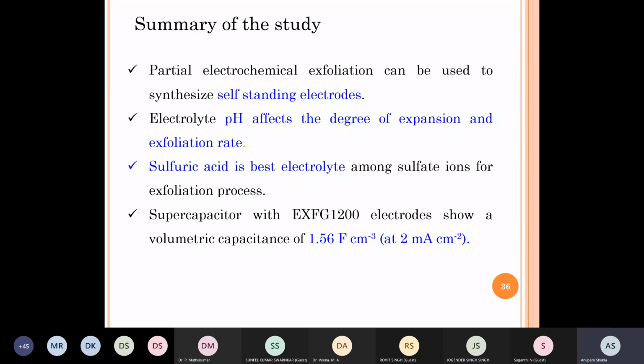Sulfuric acid amongst all the sulfate salts. So remember, this is not an absolute statement. We did not try all the salts. Amongst the sulfate-based salts, sulfuric acid turned out to be the best electrolyte. And of course, the electrode with exfoliation time of 1200 seconds shows capacitance of up to 1.56 farads per centimeter cube at 2 milliampere per centimeter square current density.